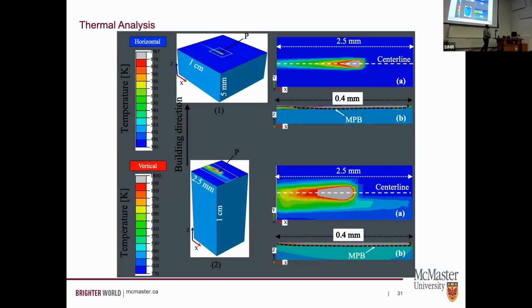And so here as well, we had to do a finite element calculation to extract from the alloy of interest what the temperature history was like. For this particular project, instead of just extracting the temperature gradient across that melt pool, what we actually extracted was the full temperature history, the full temperature formulation and profile, so that we could put it directly into our phase field formulation.